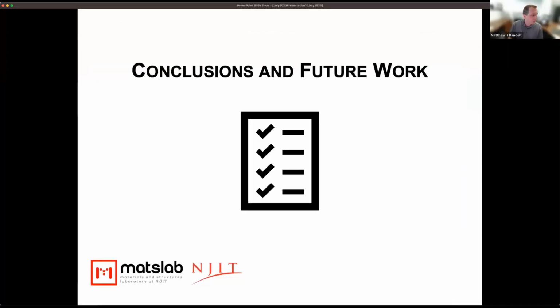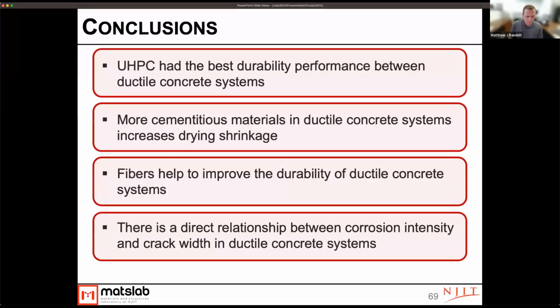So now I'll summarize with some conclusions and things that we hope to work on in the future based on this study. In general, UHPC had the best durability performance that we saw of all the ductile concrete systems. That's somewhat to be expected given the high upfront cost and the high mechanical properties. In some of the fiber reinforced systems, there's high cementitious material content, and that resulted in increased drying shrinkage. But those fibers helped improve durability performance across a range of different metrics.